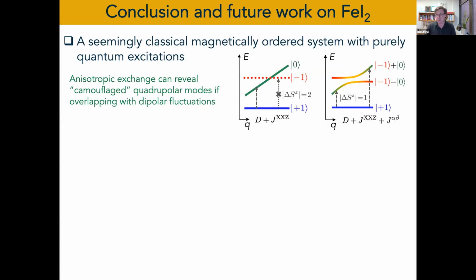I will move to the next one swiftly. But so the message is that we have a classically ordered system, but in its excitation sectors, things are non-trivial. And what we see here is that because of off-diagonal exchange interactions, we can reveal quadrupolar fluctuations that are usually camouflaged. They are a hidden sector of our excitation spectrum, but now they become revealed by the coupling J_x or J_yz here that couples these two sectors, and you see essentially hybridization between these excitations. So it's in the end quite simple.